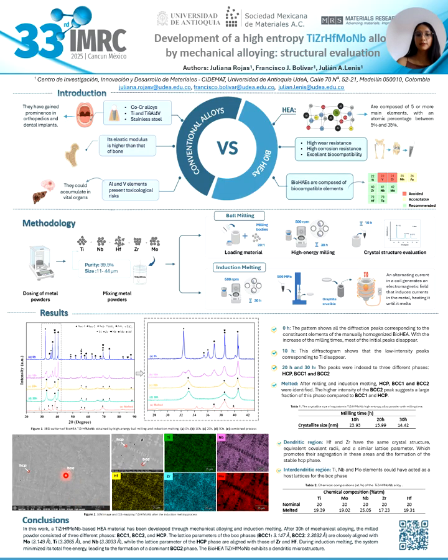On the other hand, interdendritic regions are composed of titanium, niobium, and molybdenum in a significant atomic percentage. These elements have a lattice parameter close to the calculated lattice parameter of the BCC phase. We suggest that they could have acted as the host lattice for the BCC phase.